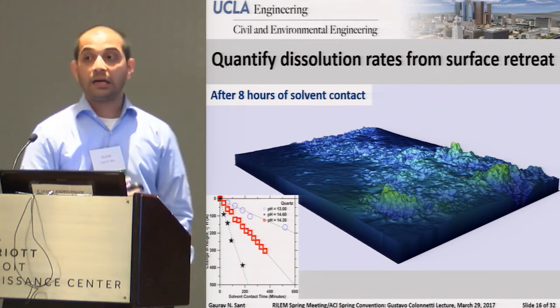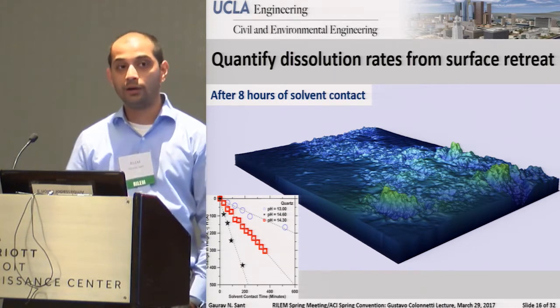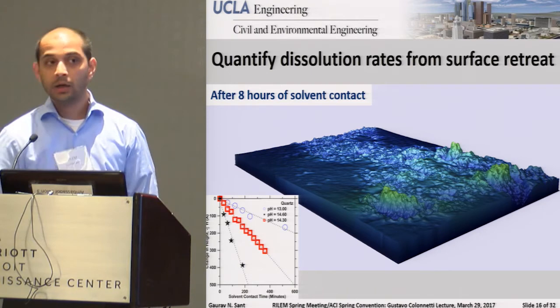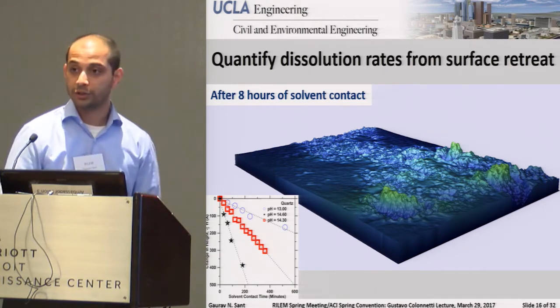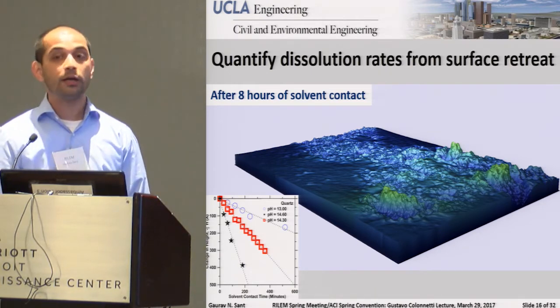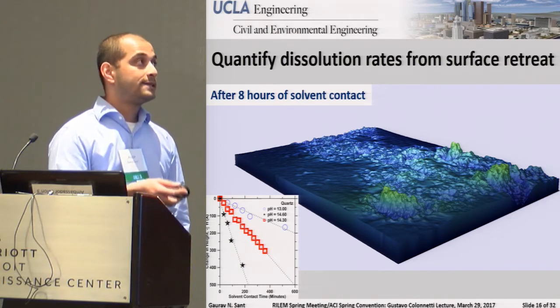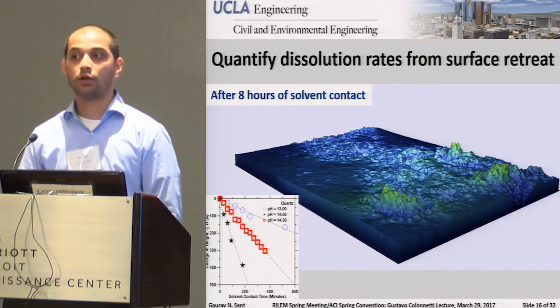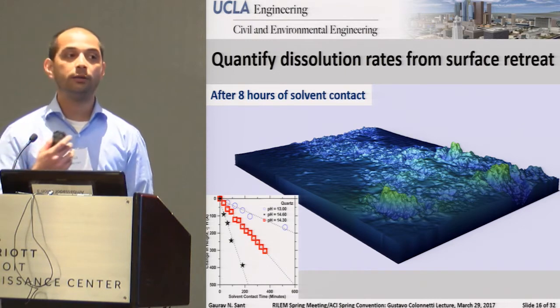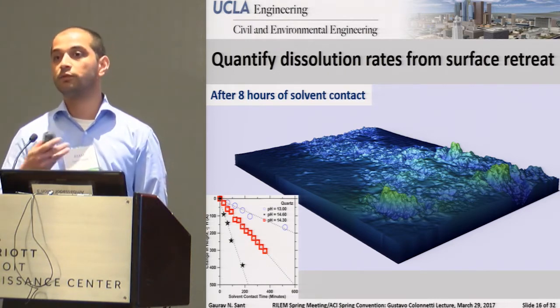On the other hand, if you're looking at glasses, for example, which can dissolve incongruently or form these alteration layers on surfaces, the results that you can get from solution concentration measurements can be pretty misleading because you've got significant incongruency in dissolution. The nice thing about interferometry is it gives you an actual mass loss, which is nice because you don't need to make any presumptions about the mechanism of dissolution.